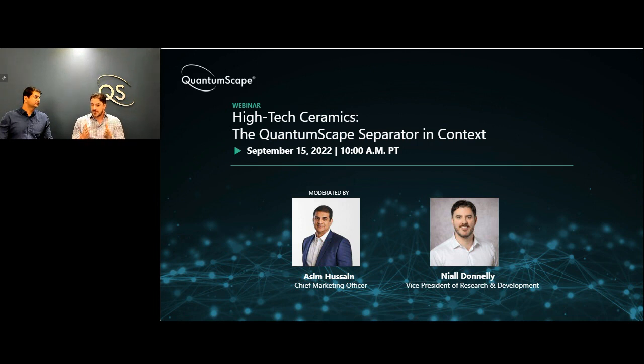The ions are actually carried by the liquid electrolyte that permeates through the porous structure of the separator. So it's the liquid itself that does the conduction. In the case of the QuantumScape separator, we have a very dense ceramic material. There is no porosity, there's no pathway for liquid through it. It's impervious to liquid. But the ceramic itself actually conducts the lithium ions. So the lithium moves through the ceramic lattice between the layers of atoms from one side of the material to the other. So it's actually the high mobility of lithium in this crystal structure that gives it its conductivity. So it's a solid state diffusion mechanism, not through a liquid medium. That's the main difference.